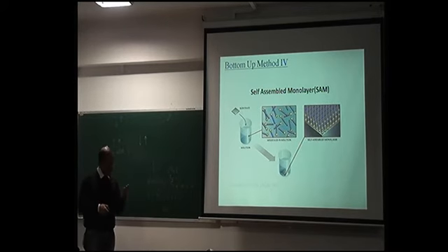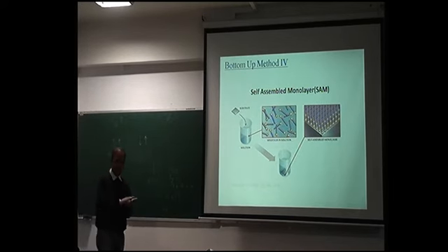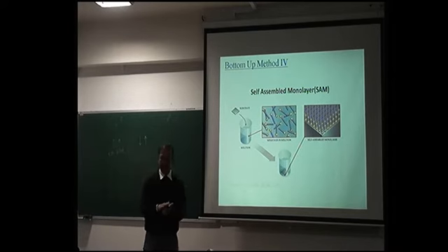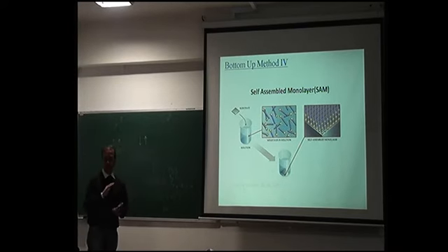and then you get another silicon substrate, coat it with gold, but if before the gold you put a layer of titanium, it will be better. That will reduce the surface energy of the silicon. And then you do a little bit of flame annealing of the gold top layer. Flame annealing will make the gold smoother, okay? Because when you make a nano gold thin film by any of the evaporation techniques, you get a slightly rough surface. And then you do a flame annealing of the gold.